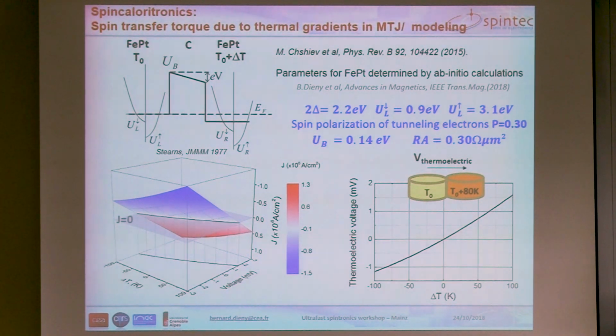I don't want to enter in too much detail at this point, but you see here the parameters that we used to describe this system with a barrier relatively low, because we want to describe these carbon grain boundaries, and carbon is a semiconductor with a relatively low barrier height. But we can calculate that with these values, actually, the spin polarization of the tunneling electron through the barrier would be 30%. And the resistance area product of the grain boundaries would be 0.30 ohm micron square. And I'm going to show that experimentally, indeed, we are very close to this value.